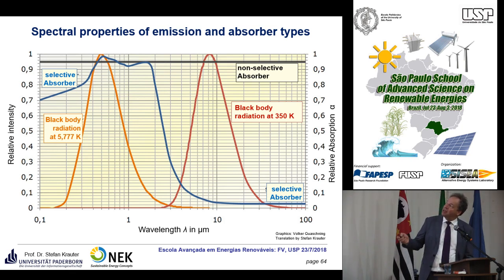That means we have the advantage here, that area is very welcome. We absorb all the sunlight and convert it into heat. On that part, here at about 10 micrometers, or 10,000 nanometers, this is the thermal radiation of your solar collector. If you have a solar collector which is 100 degrees Celsius warm, it creates infrared radiation. You can measure that. Can I have an infrared thermometer using that? This works in the vicinity of 10 micrometers. So the idea was you want to have high absorption here, but low emission in that part. So you want to avoid thermal emission here.